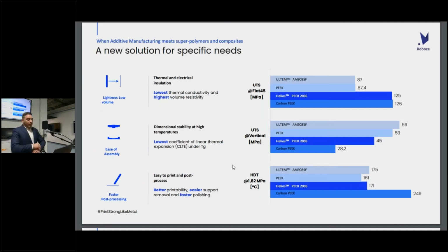So where is this needed? Well, it has great thermal and electrical insulation, even more than PEEK. Let's say that you need to isolate or shield an engine compartment from heat, and you need a wall thickness of, let's say, 3 inches with PEEK. Now you can achieve the same results with 1.5 inches, which is amazing for reducing the dimensions and the weight of your part, which ultimately, for the types of applications in aerospace or motorsport where we're strongly present, is quintessential.